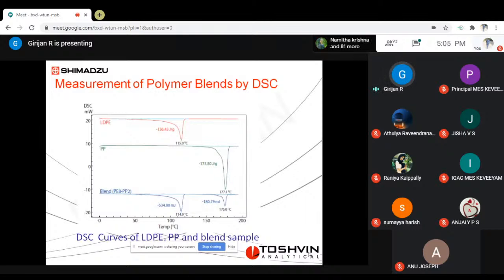Measurement of polymer blends by DSC. See, we have pure LDPE and we have pure polypropylene. We are mixing polypropylene and LDPE in a certain combination, and using partial area software, we can even quantify what the LDPE content in the mixture is and what the PP content in the mixture is.